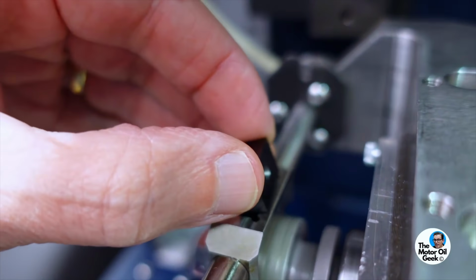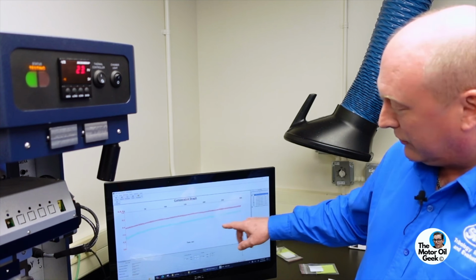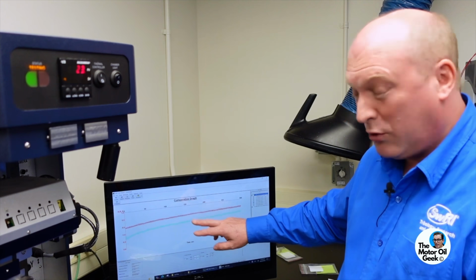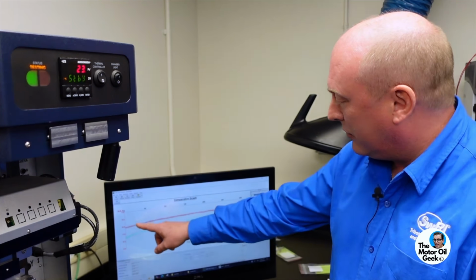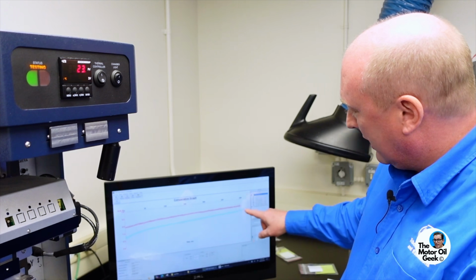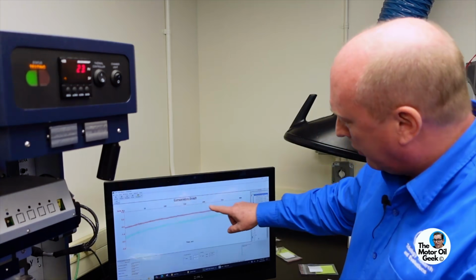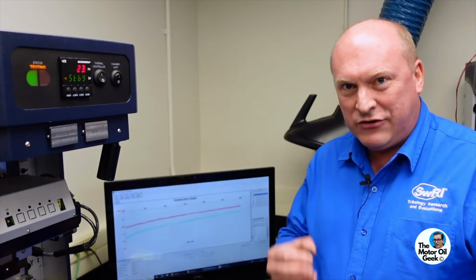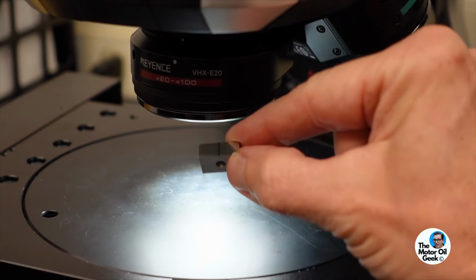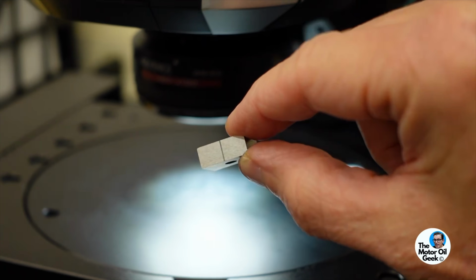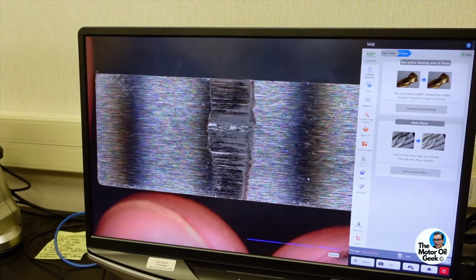Okay, so here we can see the results of those friction curves, and this is two different tests that we've performed, and we'll go into that detail a bit later. But these two friction curves here show how the block and the ring have responded, interacting with each other over time. And what we're going to do is take the block, and here's an example of a block with a wear scar, and we're going to take that over to the white light interferometer, and measure that wear scar and actually give it a volumetric value so we can compare the two tests that we run.